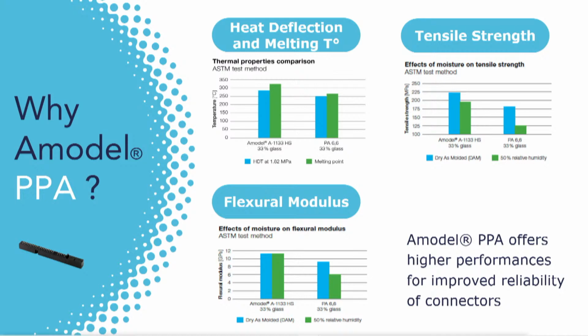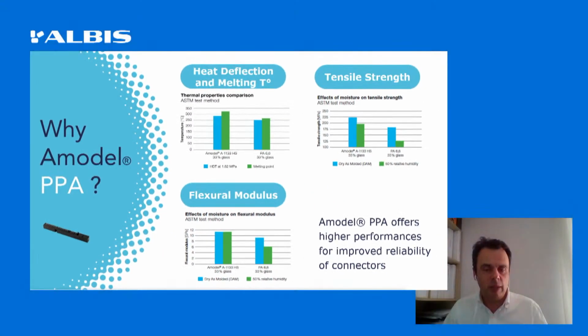It is also true for flexural modulus. Amodel PPA has a flexural modulus of 11 gigapascal, and at 50% relative humidity, the flexural modulus remains stable. PA66 starts at 9 gigapascal and loses roughly one third of its flexural modulus. Clearly, Amodel PPA offers higher performance to improve the reliability of connectors, of automotive connectors.